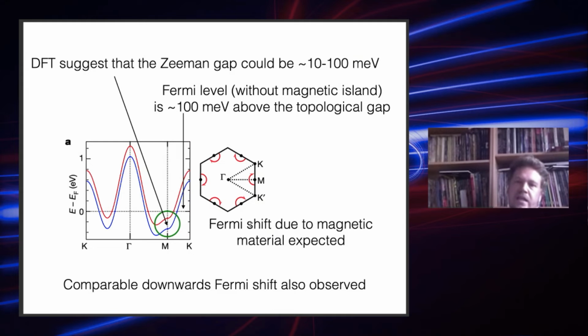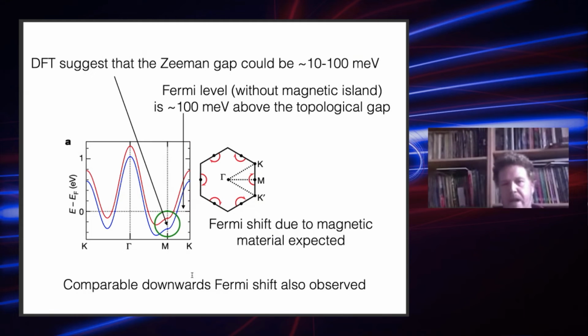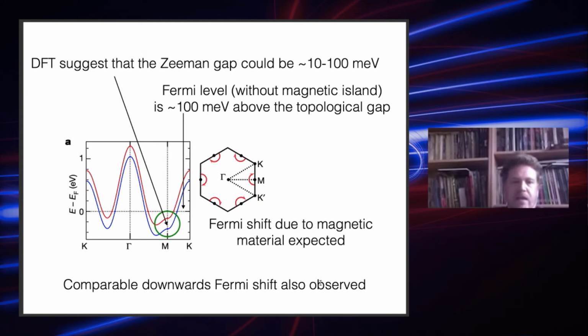And indeed, this Fermi level shift due to the magnetic contact material is expected. Obviously the pristine system Fermi level is changing, and it is due to the chemistry of these materials. It's in the correct direction, that it would shift downwards. And actually, even the experimentalists see that there is a comparable downward shift of the Fermi level in this system.